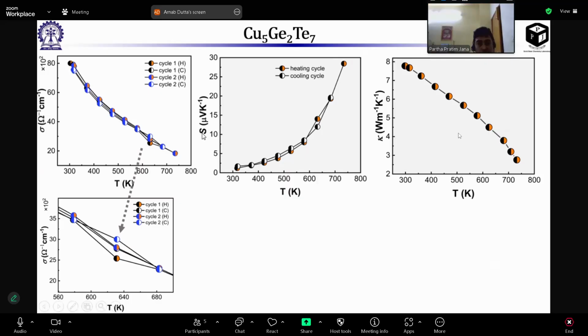Maybe Arnav, you check once. It shows that at high temperature the lattice thermal conductivity is becoming negative. That is why I did not put the graph here. You made sure that you took the T value at high temperatures, right? Because the formula is κ_L = κ − κ_e, where κ_e = LσT, so the temperature also needs to change. We already accounted for that, right? Yes, sir, we have already accounted for the coefficient, but after 500 Kelvin it's becoming negative.